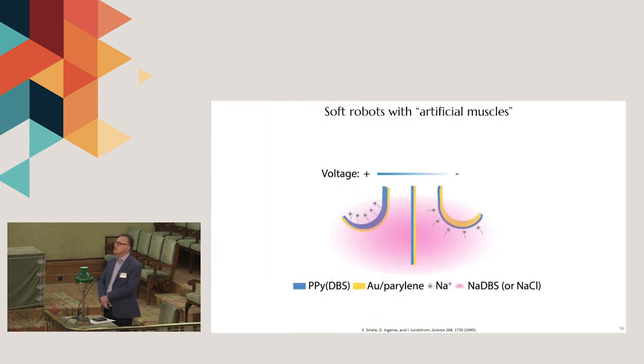Let me end with something a bit more visual and perhaps more practical. The field of soft robotics is getting a lot of attention these days. And one way you can build soft robots is to use what is called artificial muscles, where you take a conducting polymer film and you make a bilayer between it and a thin metal film. So as you polarize this structure electrically, ions can go into the polymer and change its volume. They can either swell it or when they come out, they can shrink it.